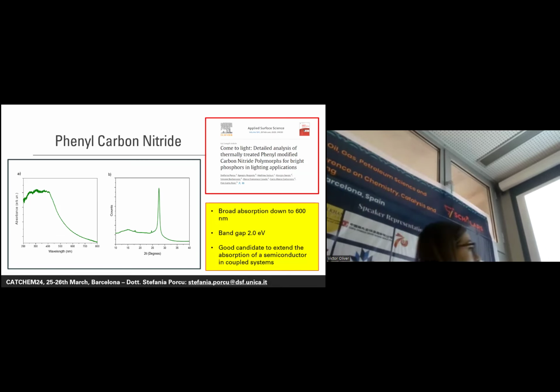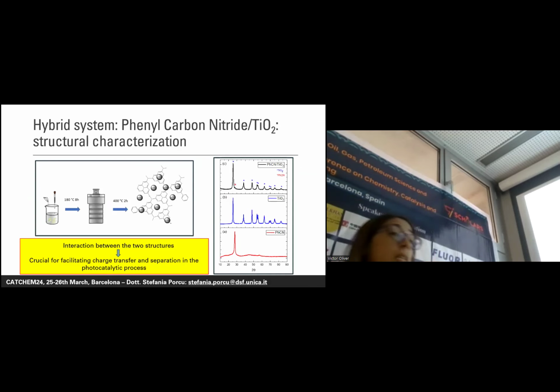So the band gap for these materials is around 2 electron volts, and for this reason, it's a good candidate for photocatalytic application. So what we decided to do was to synthesize and study a hybrid material by capping this polymer with titanium dioxide. So we did it via solvothermal synthesis, starting from the already prepared polymer and growing on the surface of the polymer titanium dioxide, starting from titanium tetrachloride.